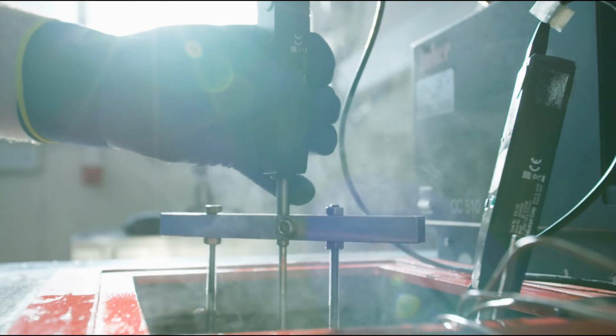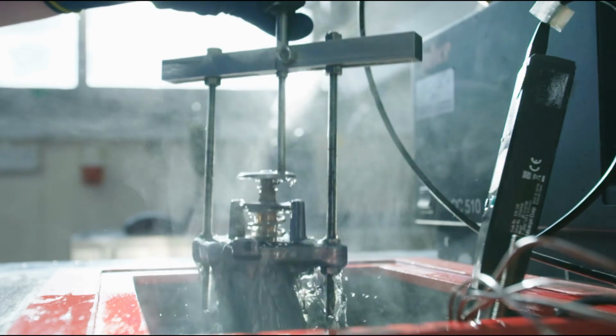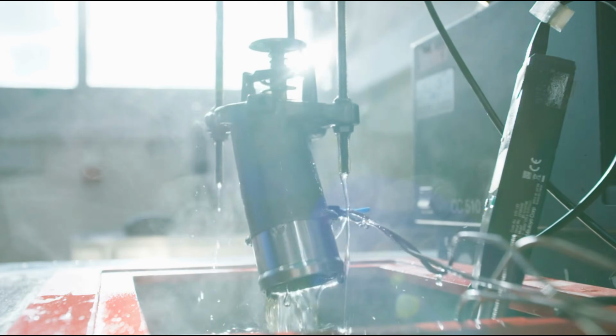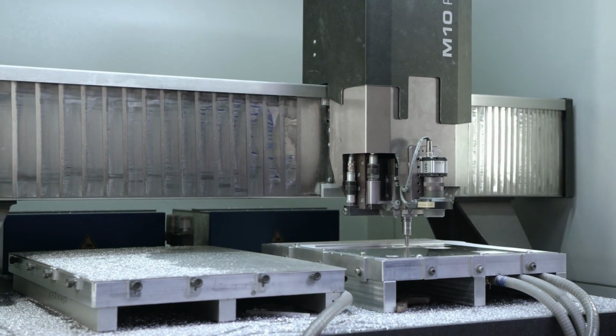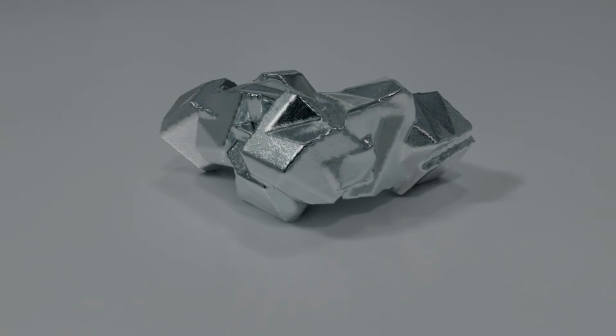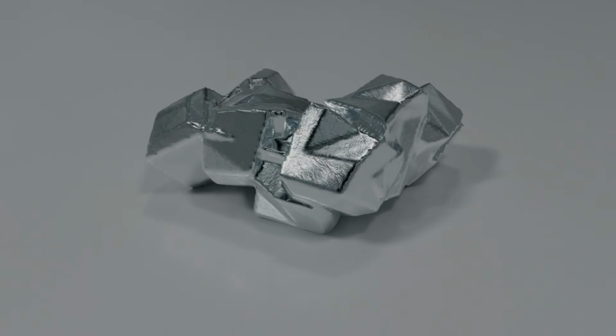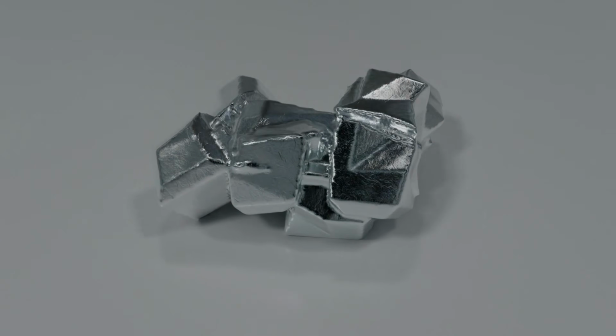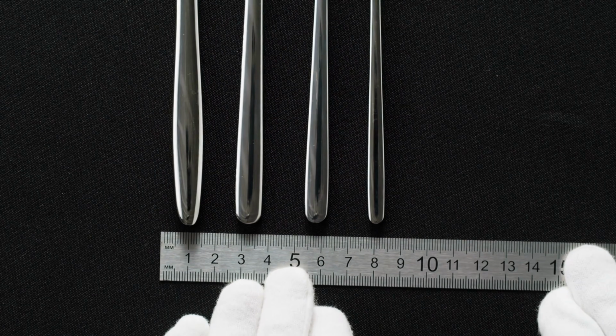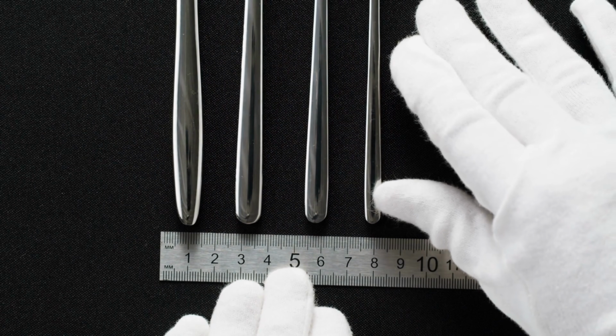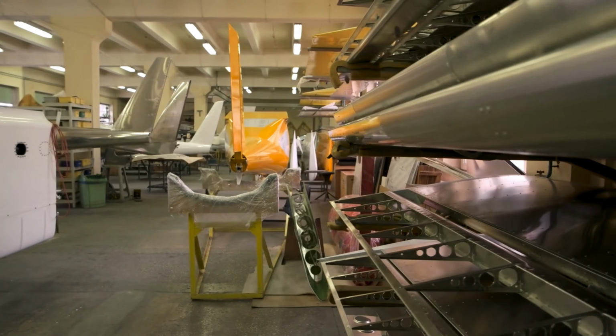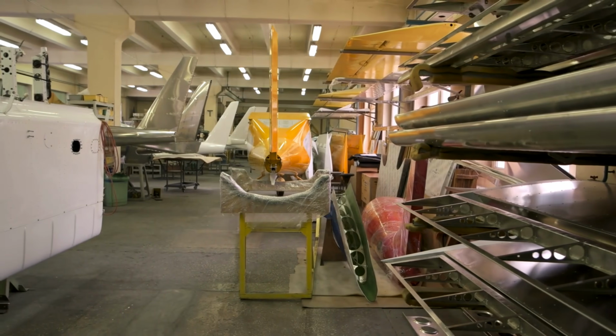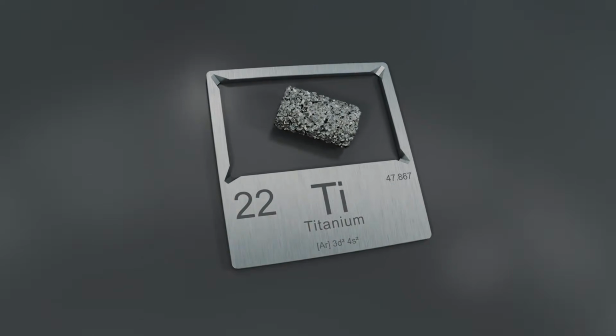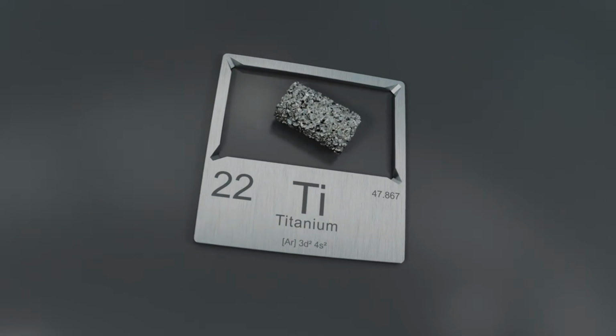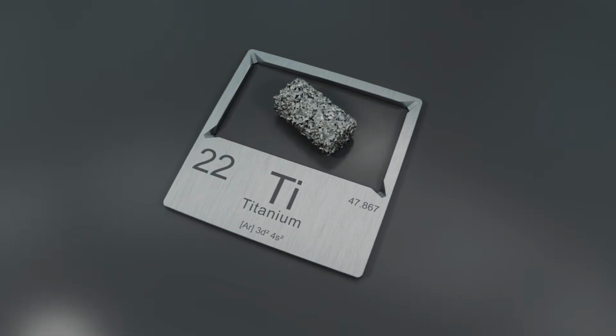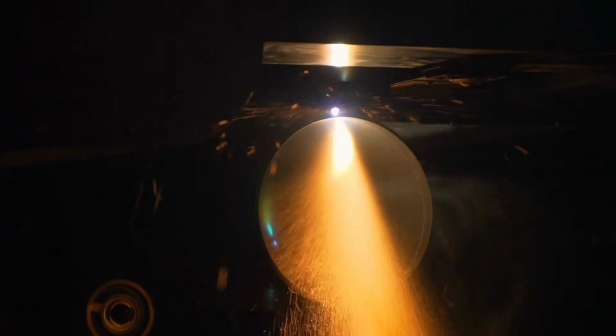Quality analysis of titanium sponge involves testing that surpasses pharmaceutical standards. Mass spectrometry systems can detect trace impurities at concentrations below 1 part per million, while mechanical testing verifies that the sponge will produce titanium with the strength and ductility required for aerospace applications. Chemical analysis checks for over 30 different elements that could affect final metal properties, because aerospace manufacturers require absolute certainty about material composition.